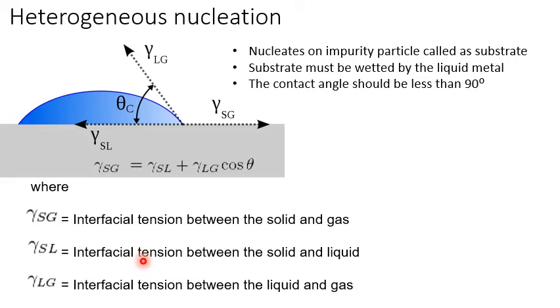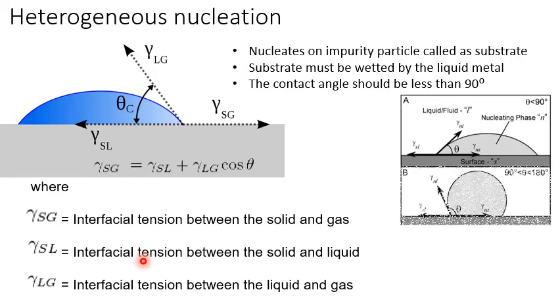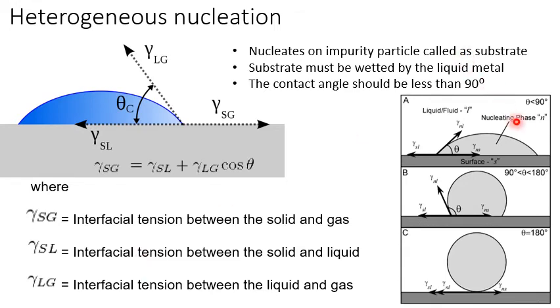In order to have favorable heterogeneous nucleation in a mold provided with impurities, the contact angle should be less than 90 degrees. So the favorable condition is theta less than 90 degrees. When theta c is equal to 180, or between 90 and 180, these conditions are not favorable for heterogeneous nucleation. The surface should be wetted properly, and only then will the contact angle be less than 90 degrees.